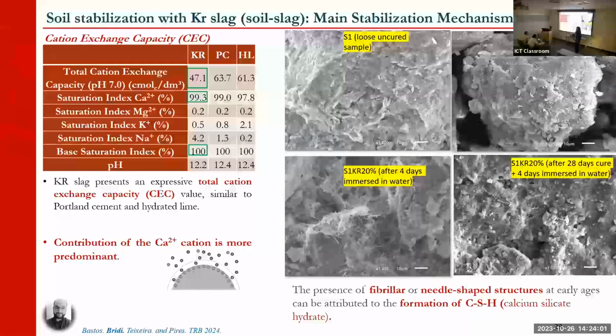But we wanted to go further and see, what is happening? What is KR doing with this clay soil that is justifying this good result? So another student did some microscopic analysis, microstructure analysis, and chemical analysis. He quantified the cation exchange capacity of the KR, and he observed that the total cation exchange was 47 and was similar to values found for common binding agents such as Portland cement or hydrated lime.